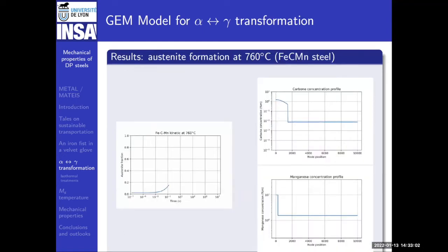Yes. I have a question. It seems that in the third plot, you have a creation of an interface there. In fact, no. The interface is already there, and you can see where the interface is at each time. But what happens here is that the interface moves, but the manganese has no time to diffuse. So the interface moves, and manganese is flat. This is what we call para-equilibrium. It means that only carbon is at equilibrium, but manganese is the same before and after in ferrite and austenite.